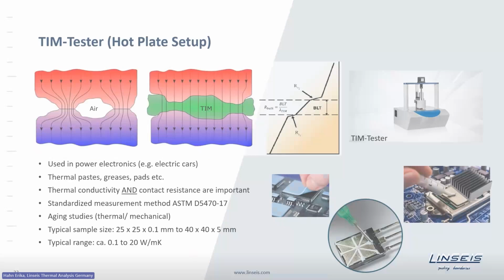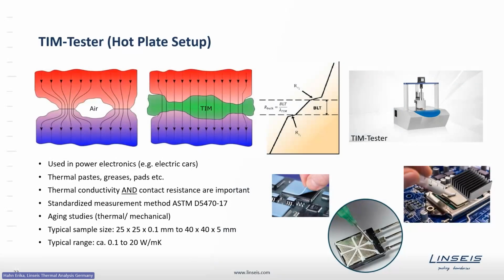which is especially designed for so-called thermal interface materials, which act as a gap filler or void filler in between the contact of two different materials, mostly in electronics. Most of you probably know thermal paste, gap fillers or thermal pads, where the electronics will be in contact with a heat sink, to remove the heat from the electronics and avoid damage.